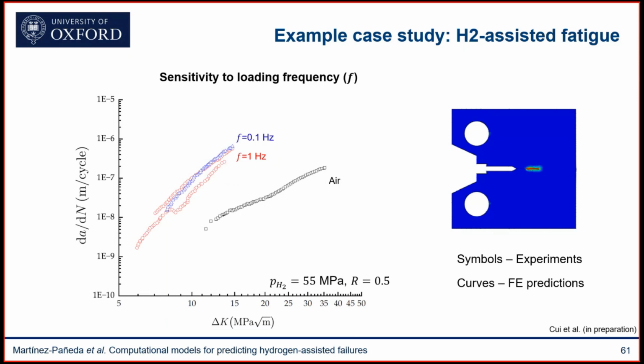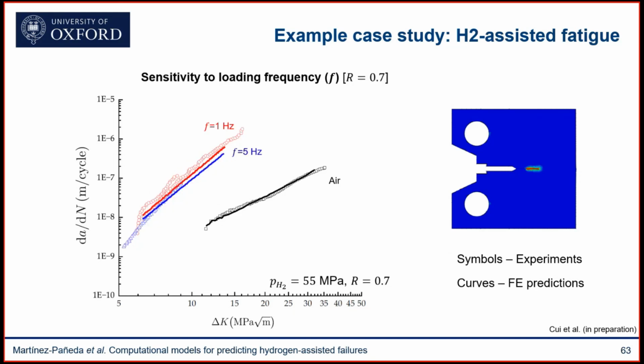They also have experiments for different loading frequencies. Again, not touching anything in our model, I'm just going to change the loading frequency. And again, a very good agreement with experiments. And this is for a load ratio of 0.5, but they also have data for different frequencies at 0.7.